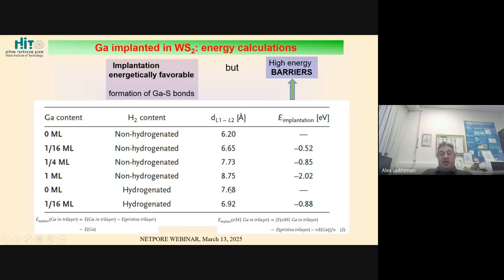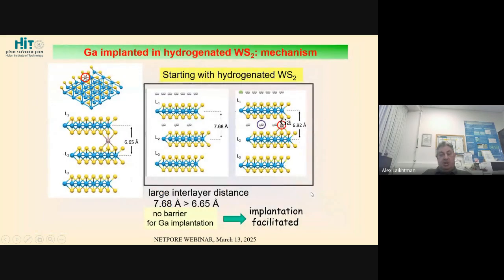Remember that in the case of intercalation of hydrogen, the interlayer distance, because of this hydrogen, can extend up to 8 or 8.5 angstroms. In the average case, 7.68 angstroms. In this case, we don't have any barrier. So when we start with already hydrogenated WS2, then large interlayer distance means implantation is facilitated.